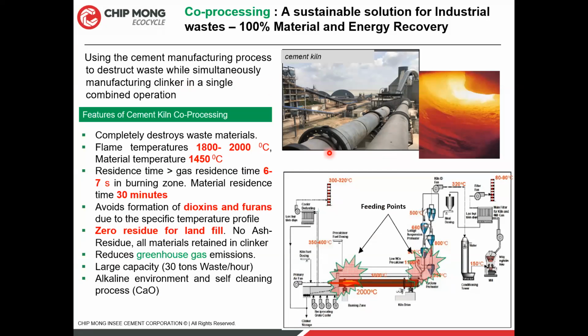So what is co-processing? Co-processing basically means we are doing two activities simultaneously without compromising any activity. That means we are producing the clinker, which is the semi-finished good of the cement, and at the same time we are disposing the waste in parallel. That is called co-processing. So the cement kiln is one of the perfect infrastructures to dispose the waste, even the most hazardous waste. Why? There are two main factors of the cement kiln: one is temperature, the other one is the residence time.